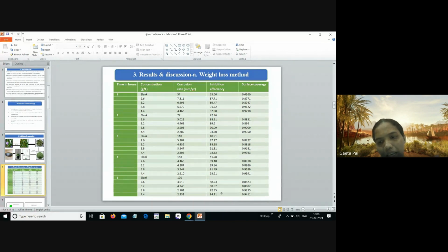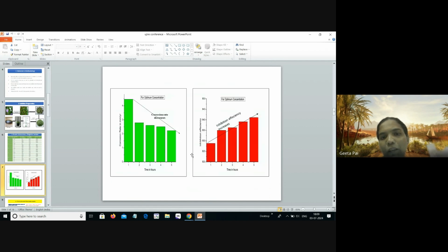It indicates that the effective constituent present in the Putranjiva roxburghii will adhere to the metal surface and it will inhibit the corrosion process. That can be graphically shown: as the time increases, the corrosion rate goes on decreasing. That indicates that the metal dissolution process decreases. And on the other hand, as the time increases, the inhibition efficiency increases.